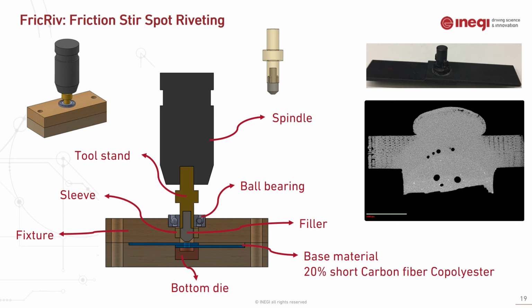Parallel to friction stir welding and the development that I mentioned, we are developing and patenting a new joining process, which is a combination of friction stir spot welding and riveting process. With this concept, a rotating tool will hold a filler material which is consumable, and the material could be same or different than the base material. However, those fillers would stir the base material and mold the rivet on the two sides. As you can see on the right side, that is the actual joint specimen, and on the bottom is the X-ray of the joint area.